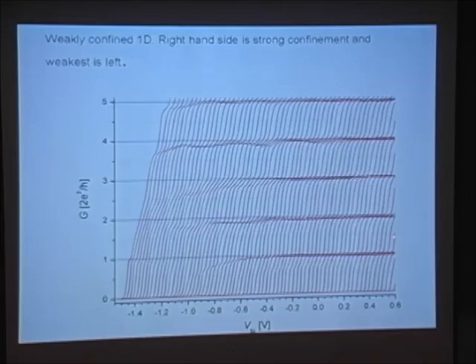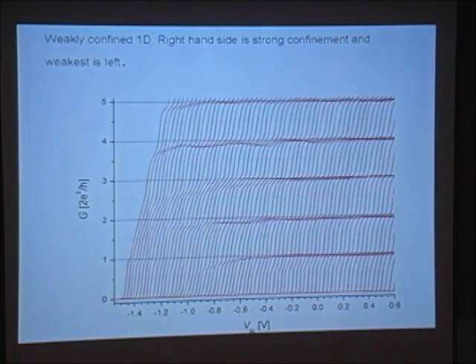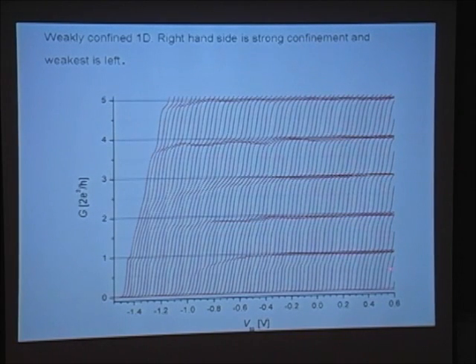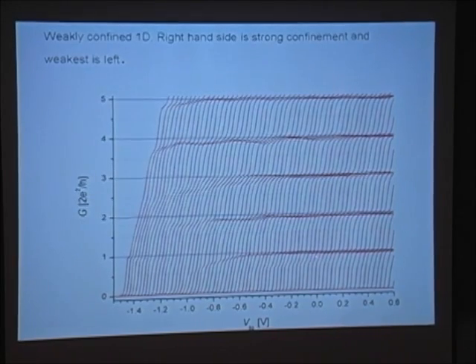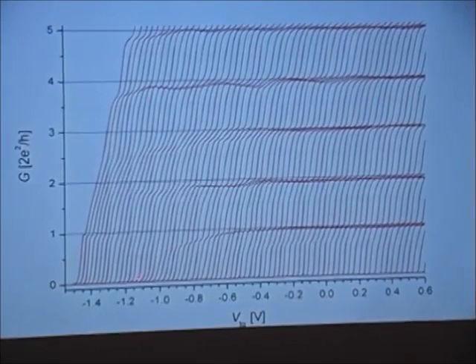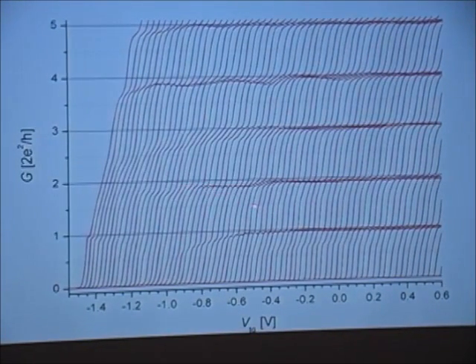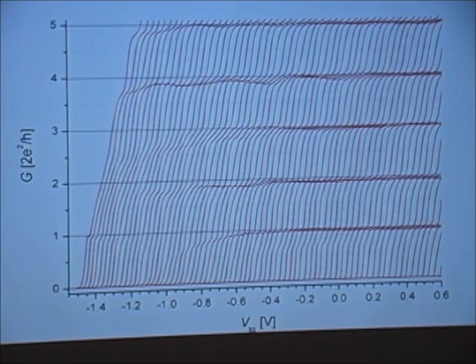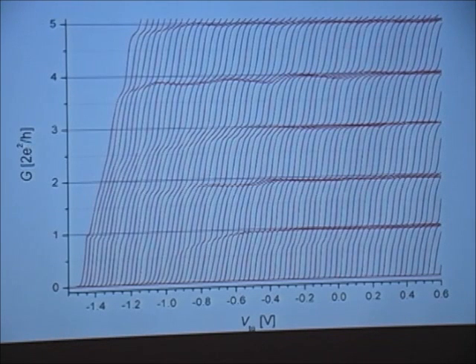So how can we see this? Well, this is an example, actually. This is what happens if we take a one-dimensional system. As I mentioned before, its resistance goes in units of 2e squared upon h, 4, 6, and so on. This is strongly confined, and what we're doing here is repeating this experiment, but reducing the confinement. So now it can actually spread apart. You'll notice that this first level at 2e squared upon h has disappeared, and it now jumps up to somewhere near 4e squared upon h. That's 2 levels. So this is an example of the formation of these rows in a weakly confined electron gas when we weaken the potential and allow the electrons to move sideways.